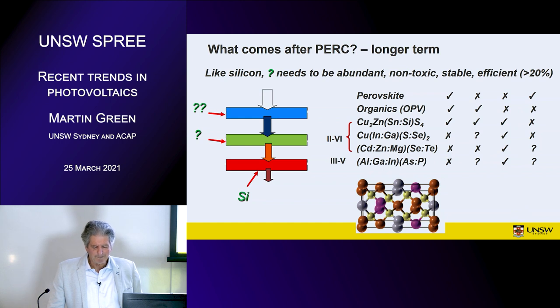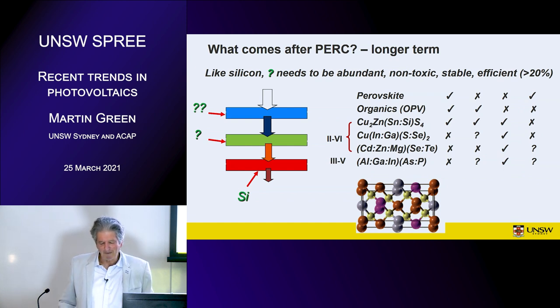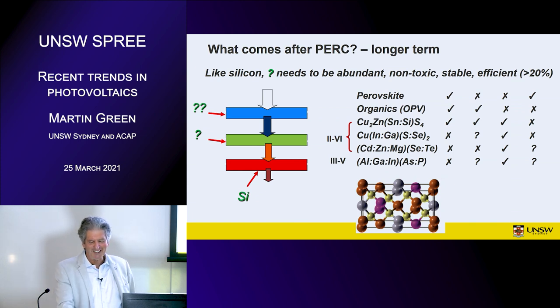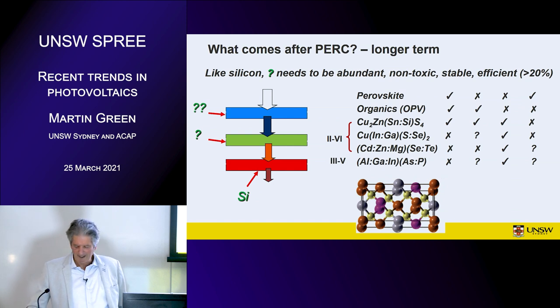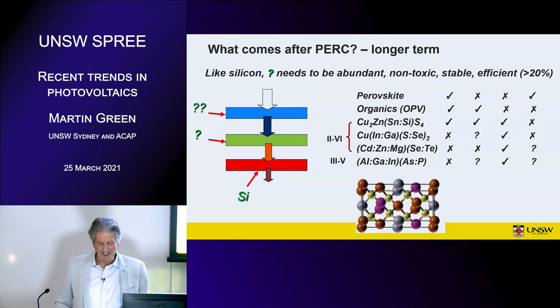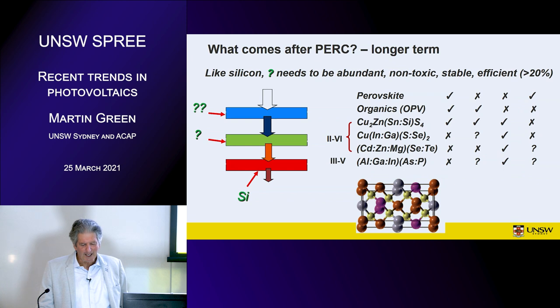And then you've got the traditional semiconductors, the diamond or silicon type structure. Artificial silicon is what I call them. But if you combine the right elements from the periodic table in the right proportions, you can synthesize material with the silicon crystal structure and similar properties to silicon, except that you want wider band gaps, which is quite easy to get. But if you look at the contenders, none of them have four ticks. CZTS is the closest, it's got three, but it hasn't got the efficiency, which is probably the really important one to have the tick against. And then some of the others have problems with stability and toxicity and so on.